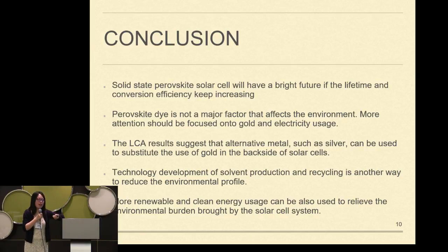And the other major conclusion from our research is perovskite dye is not a major factor that affects the environment. This is because in the process to prepare a perovskite dye, the major contribution is from the organic solvent usage rather than the perovskite dye preparation. So we think we should put more effort to improve the technology of organic solvent recycling rather than concentrate our effort on the perovskite dye preparation.